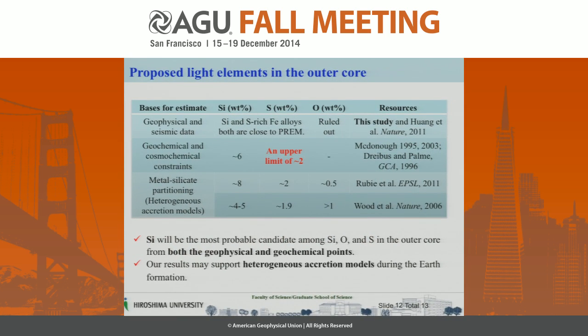Because currently there are some geochemical and cosmochemical constraints that give an upper limit of sulfur of just 2%, silicon will be the most popular candidate among sulfur, silicon, and oxygen in the outer core, from both the geophysical and the geochemical point. Our results also may support the heterogeneous accretion models during the Earth's formation, which predict about 4 to 5% silicon in the Earth's core based on the metal-silicate partitioning data.